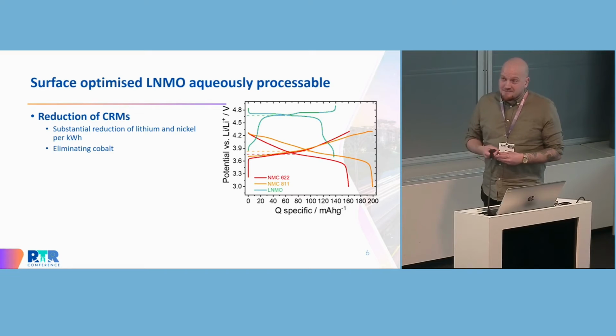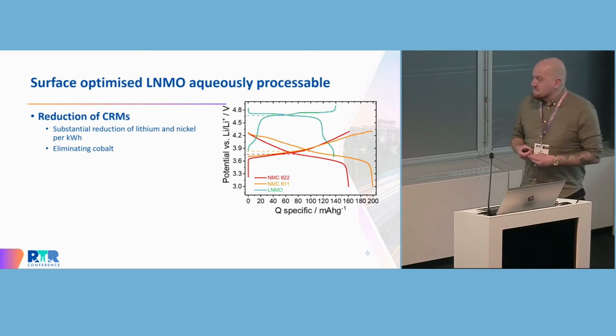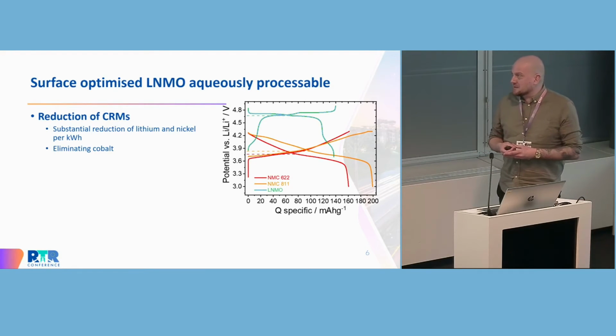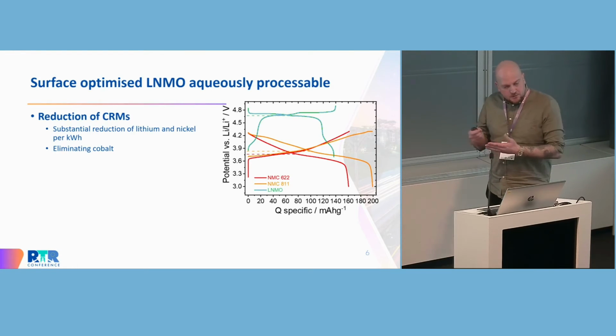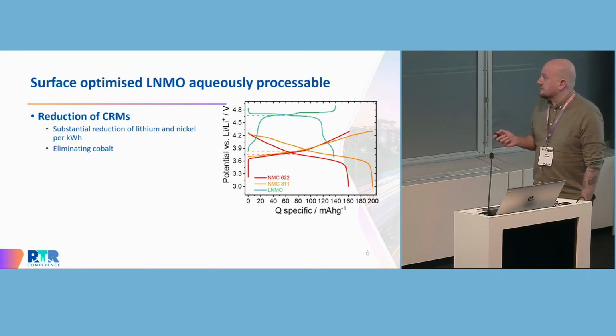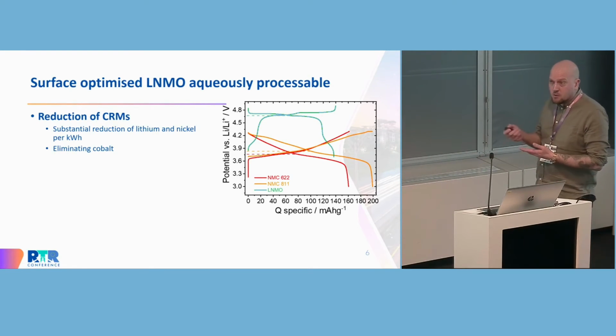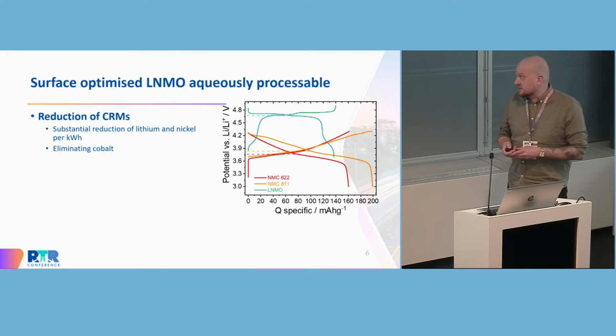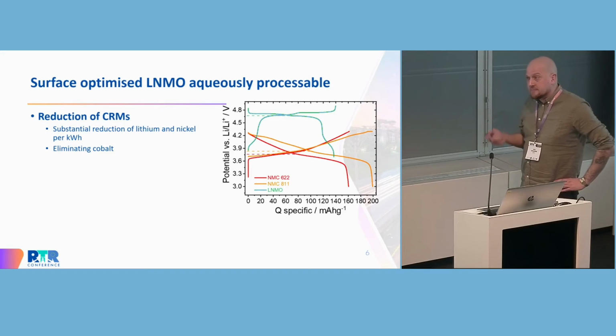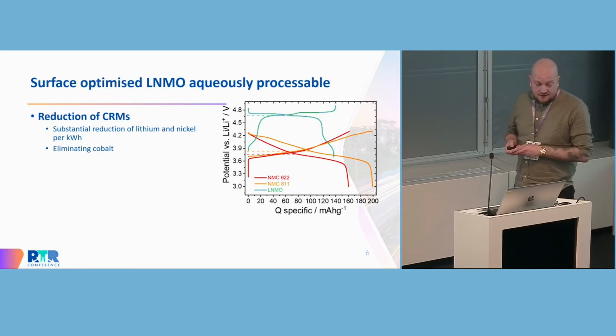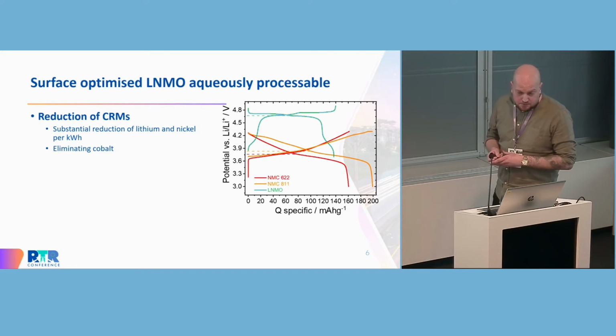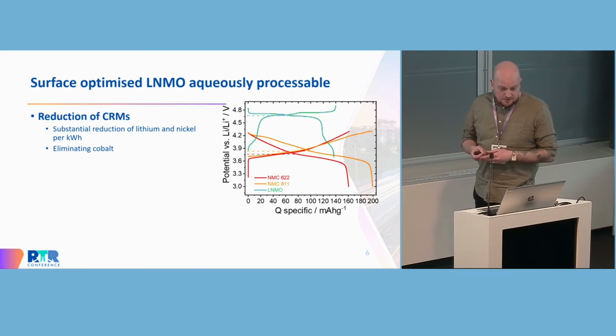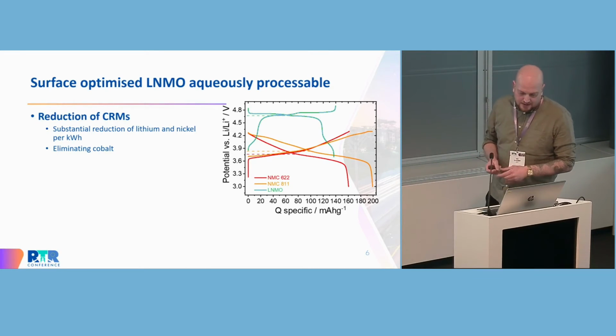Then we do not have that many metals left, unfortunately. But LNMO does substantially reduce the amount of nickel and lithium per kilowatt hour, while of course it's cobalt-free, it eliminates cobalt. And if we just see here, we see that the capacity of LNMO is actually quite a bit lower than regular NMCs such as 622 or 811. However, it also operates approximately 1 volt higher than these. And energy is, of course, the product of capacity times voltage, so the penalty in energy density is not as high as it looks.